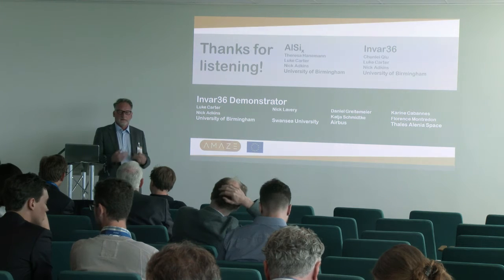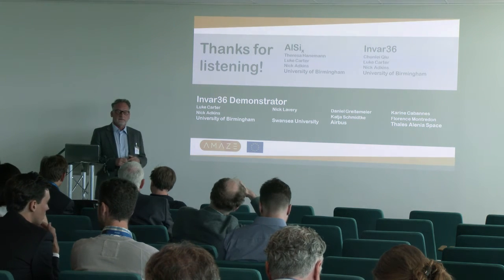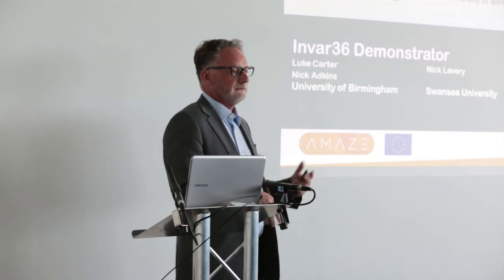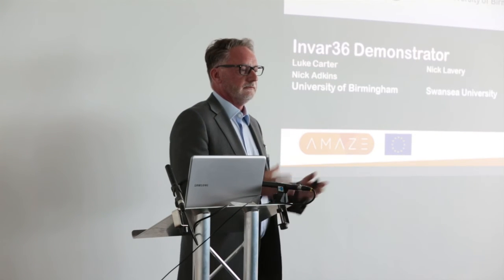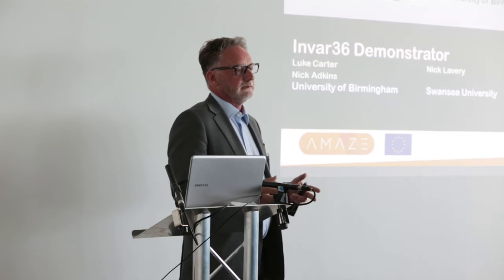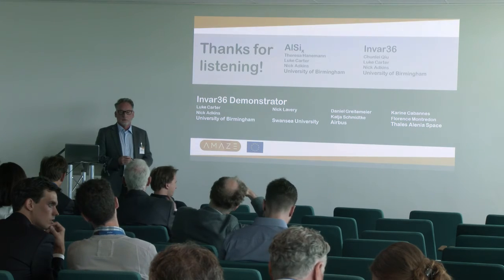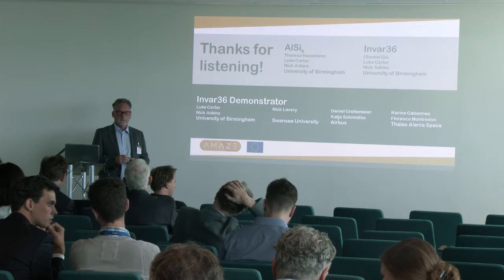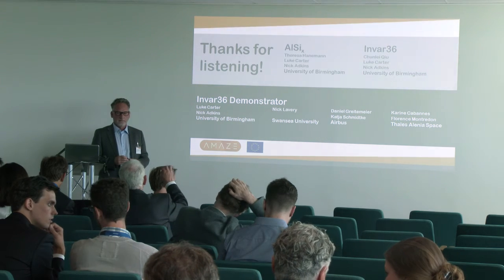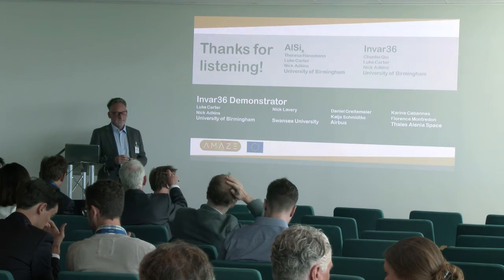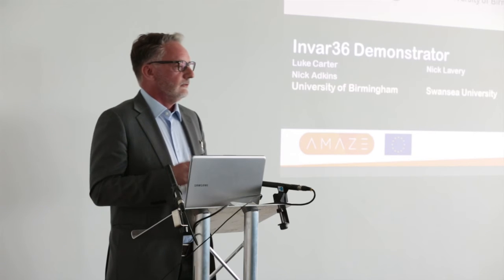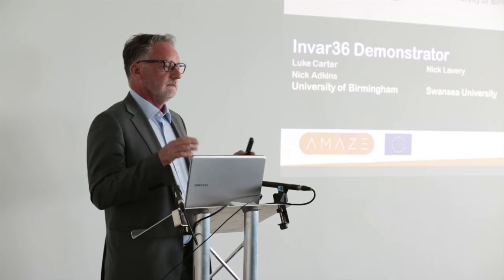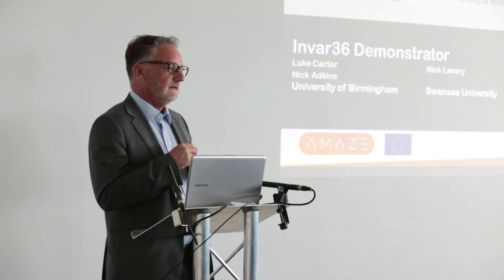For the other stuff we made by blending. So we took the normal standard aluminium silicon 10 material, which we process a lot of, and it was just blended with the silicon either at 15% extra or 40% extra for the two different trials. Pure silicon powder blended in, that's right. Which is why you were seeing on one of those pictures maybe a silicon particle. So getting all of the silicon to melt within the melt pools